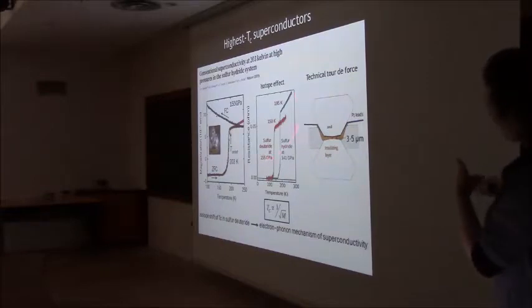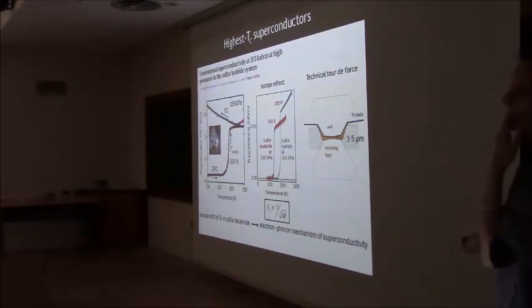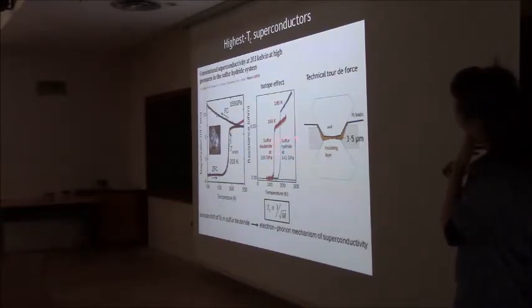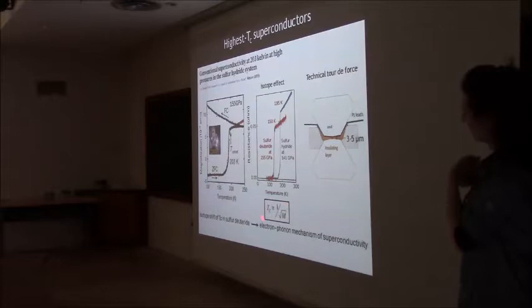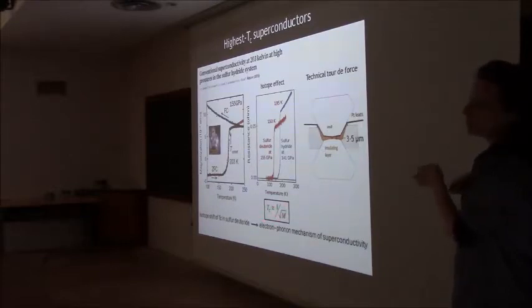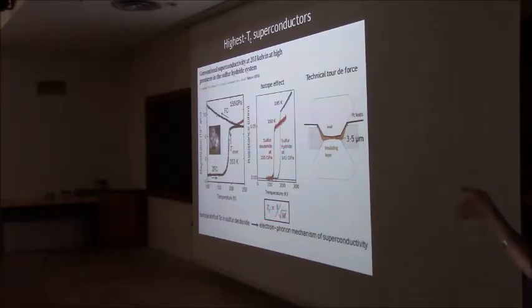And they also checked the isotope effect. So they used this compound and kept sulfur but changed hydrogen to deuterium. And they see a shift of Tc, which is expected. Deuterium is heavier than hydrogen, so Tc is a little bit smaller. And they don't get exactly this ratio, but the effect is there. So it's evidence that it's phonon-mediated superconductivity.